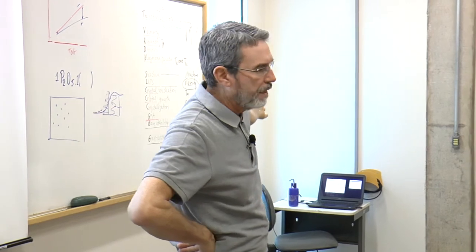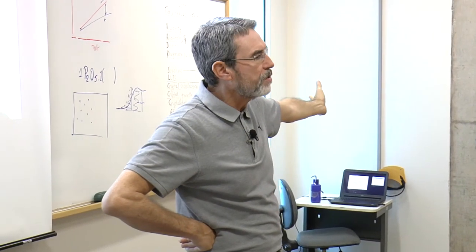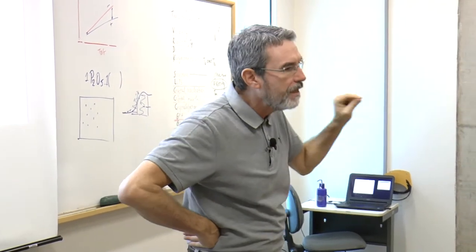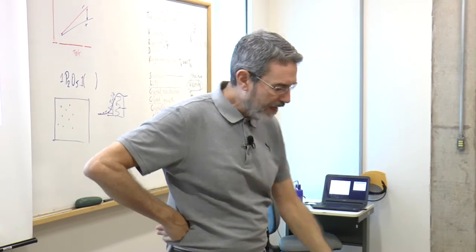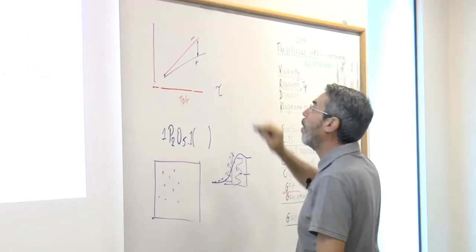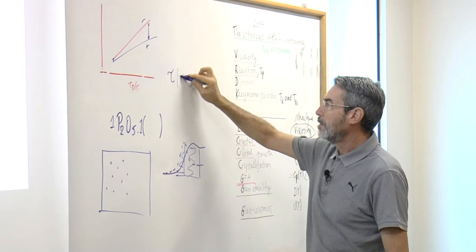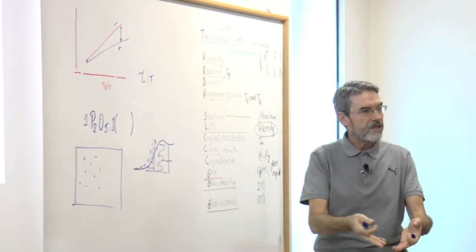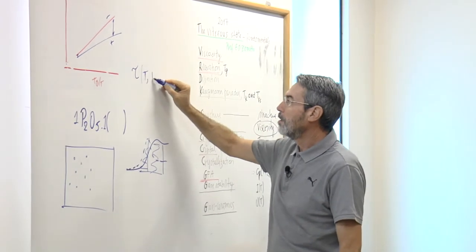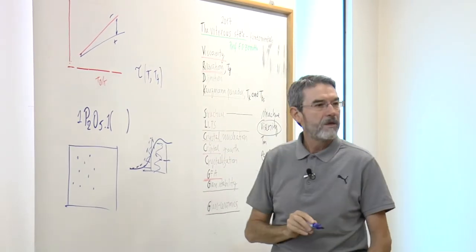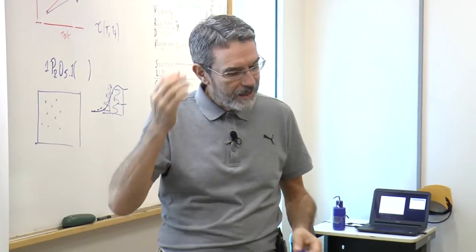You see, next week we'll talk about relaxation processes. And the speed of relaxation depends on the fictive temperature. It's very interesting because the relaxation times, tau, next week we are going to see, depend upon the actual temperature that we are studying and also on the fictive temperature of the glass. So glasses are interesting. They memorize their thermal history.